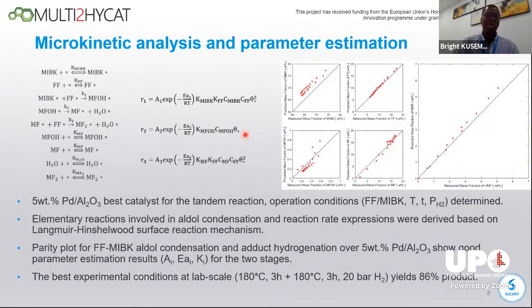So here I just give you a snapshot of the microkinetic analysis as well as the parameter estimation after the catalyst screening of different possible candidates. 5% palladium on alumina was chosen as the best catalyst for the tandem reaction. And different operating conditions, such as the molar ratio of furfural to MIBK, temperature, time, and hydrogen pressure, were determined. The elementary reactions involved in the aldol condensation are highlighted on this scheme, as well as the next step for the hydrogenation. They were derived using the Langmuir-Hinshelwood surface reaction mechanism.